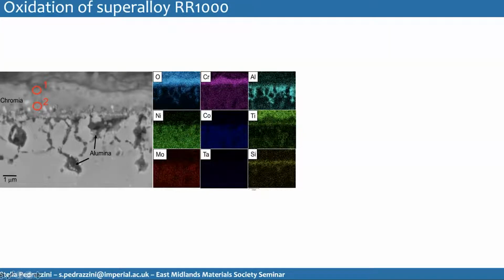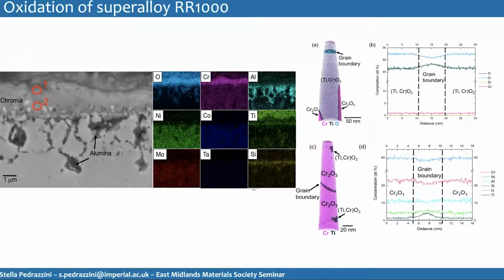It can give us an idea of where these oxides are and what they are, but atom probe can really tell us the exact chemical composition of these oxides. So in this case, I picked up 2 needles from this sample, one from the very outer surface and one from the chromia scale. They're indicated with the red 1 and 2 on the image. And the top figure here is needle number 1. And it is made of titanium dioxide, principally, with a grain boundary at the top.